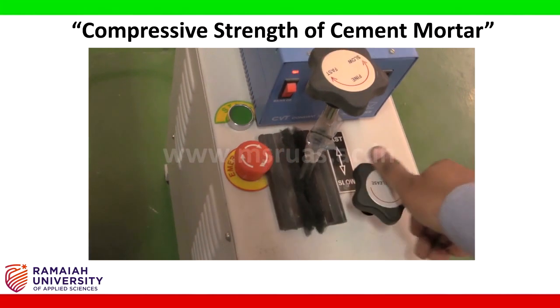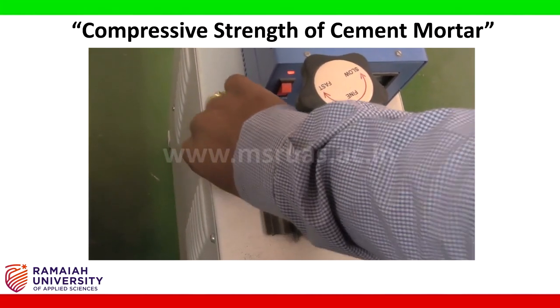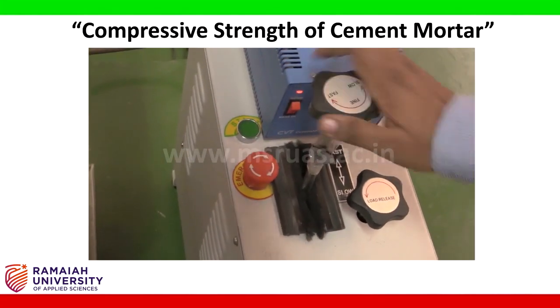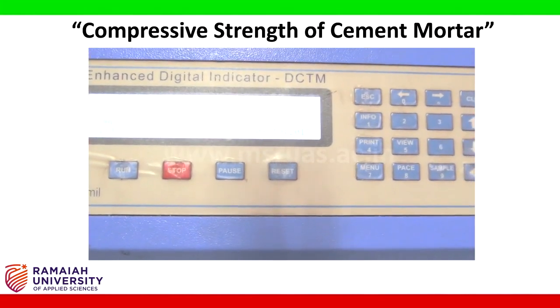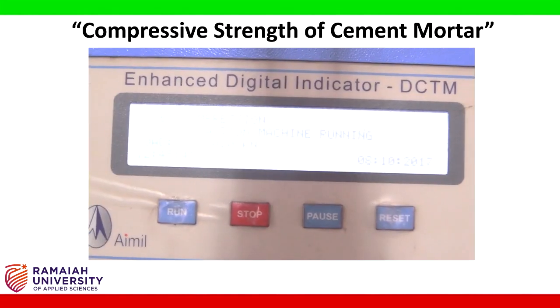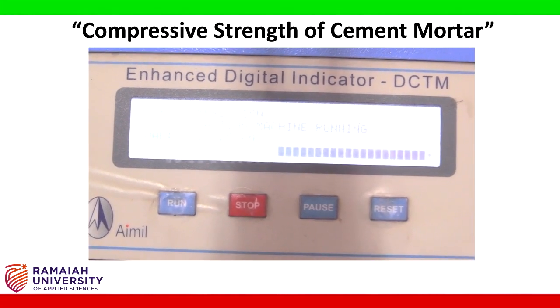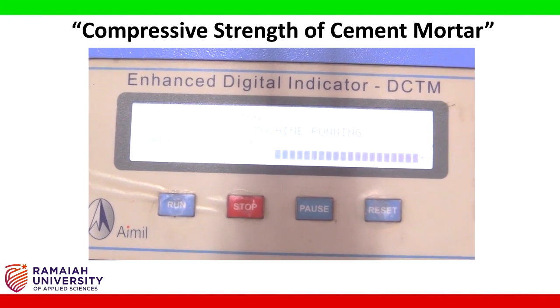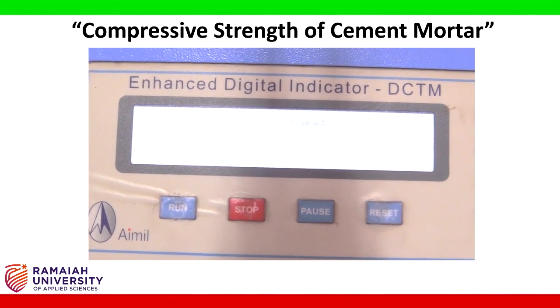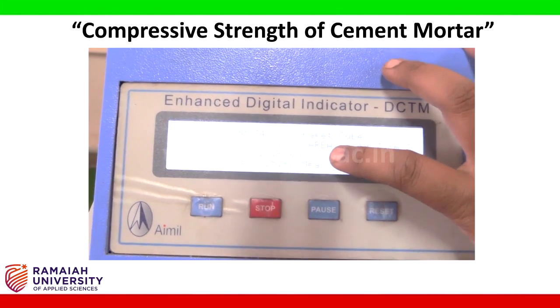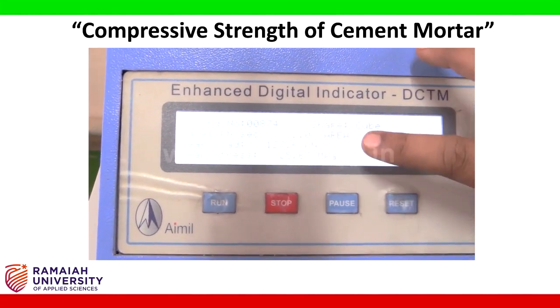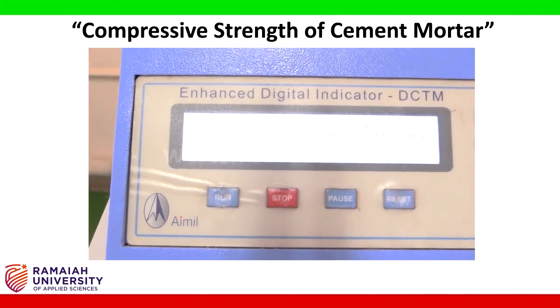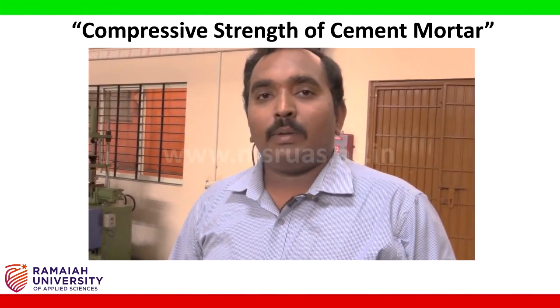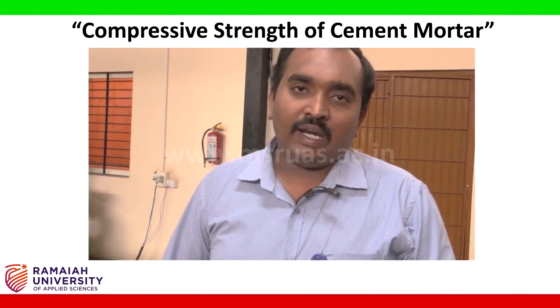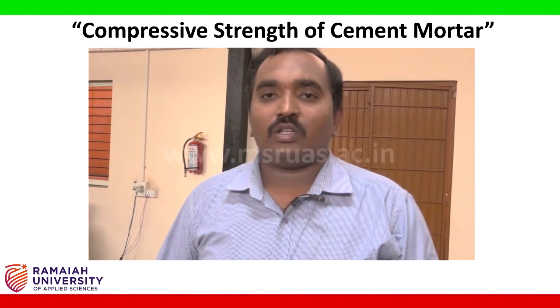Before running, make sure that your load release valve is locked completely and your emergency button is removed. Give a start command to your hydraulic jack and run the setup. It gives indication that the sample is broken. It is going to give you a peak load. As I gave the area earlier, it is going to directly calculate the peak stress. Depending upon the compressive strength you obtain, you are going to get the grade of the cement. Generally it will be more than 53 Newton per millimeter square for 53 grade cement. This completes your experiment, that is the compressive strength of cement mortar cubes.